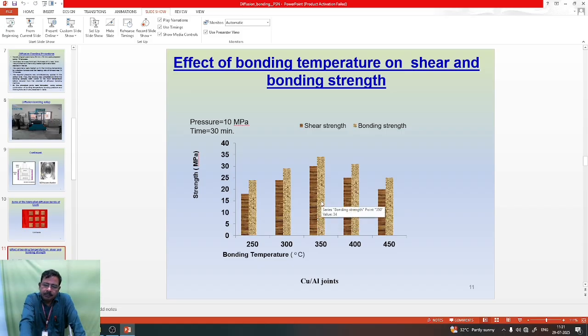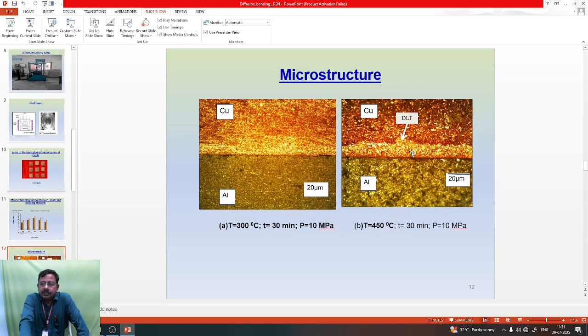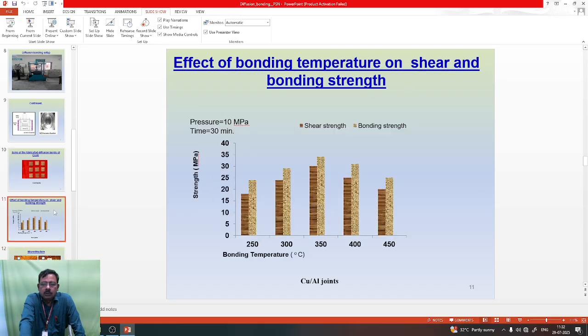Here when the bonding temperature increases, the diffusion layer increases. Diffusion layer, look at this diagram. This is a diffusion layer thickness. When the temperature increases, the diffusion layer thickness increased. So we can get the higher strength when the diffusion layer thickness is optimal. Okay, here the bonding temperature increases the diffusion of atoms. The diffusion of atoms increases, by which the metal surface of the contact will be optimum.